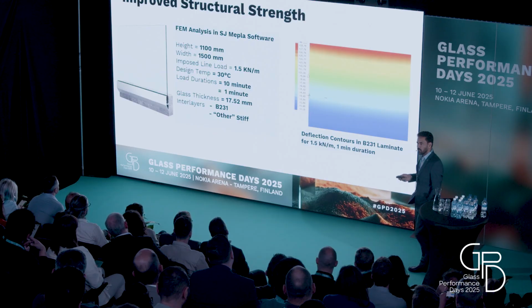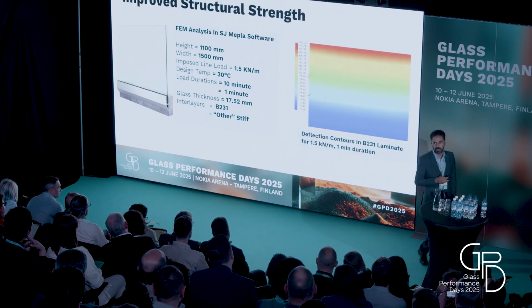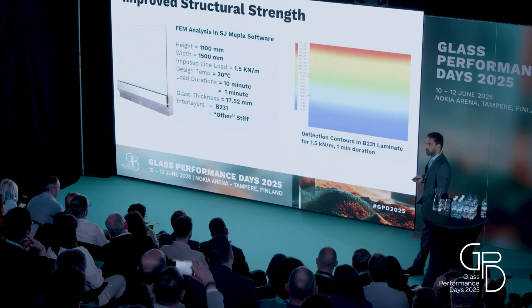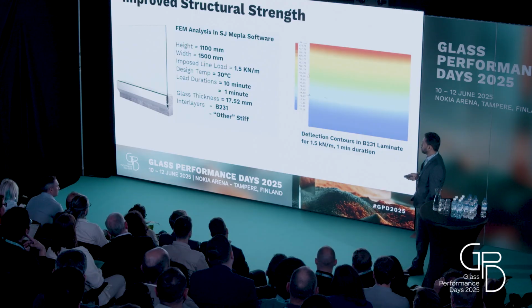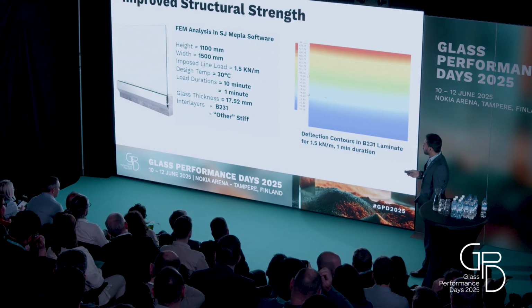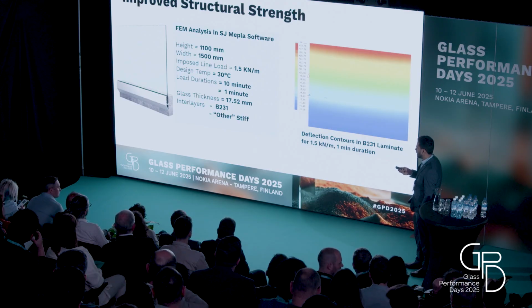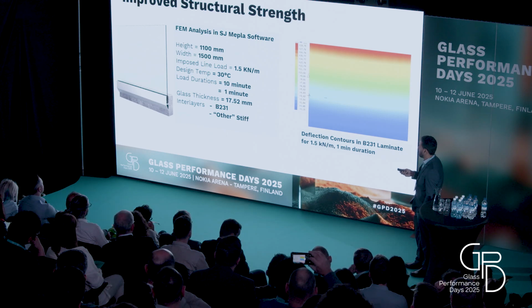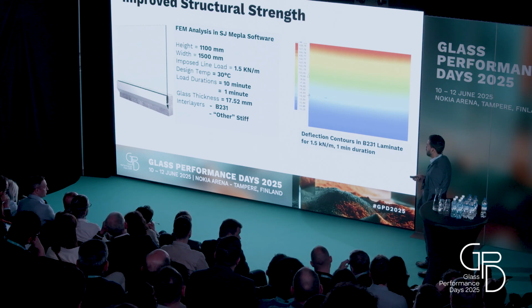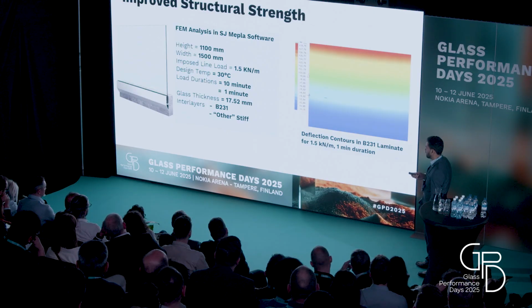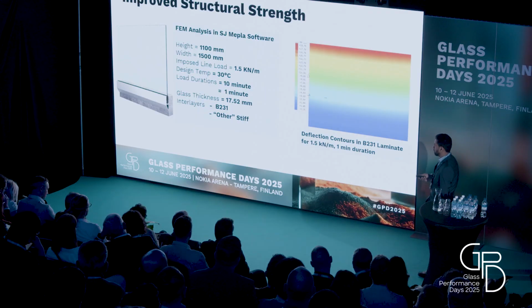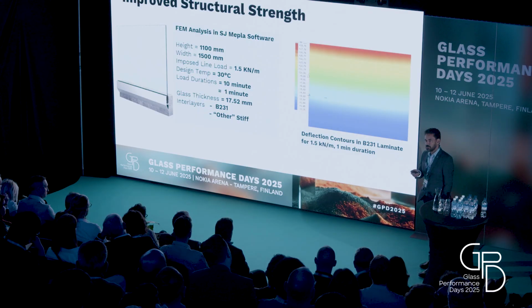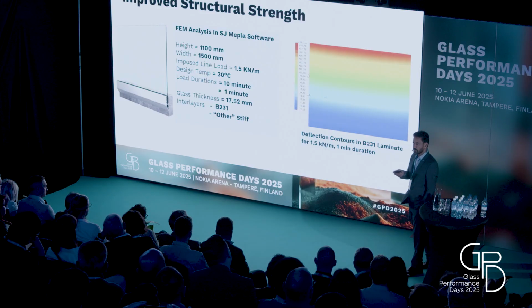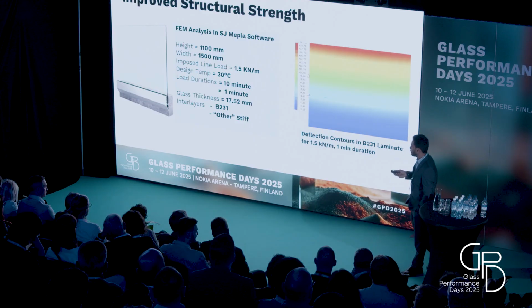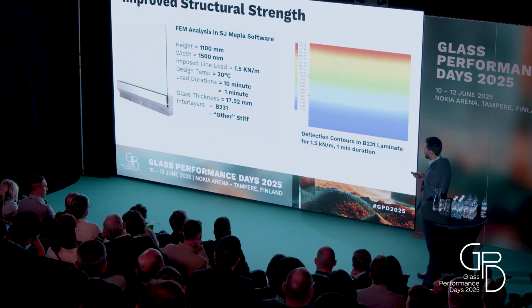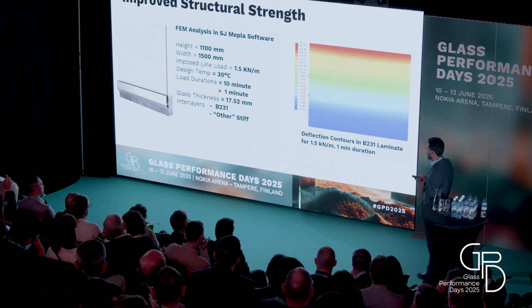Now we have seen that this improved stiff PVB has a higher Young's modulus, and the question is what this can do for the engineers. The first step is to do a finite element simulation in Mepla software. I analyzed a cantilevered glass balustrade, supported at the bottom edge with a linear support, with a standard height of 1.1 meters, subjected to a line load of 1.5 kN per running meter, and a design temperature of 30 degrees centigrade. I analyzed two different load durations, 10 minutes and 1 minute, because the duration of the live load varies between country standards. The construction was 17.52, with the interlayers being B231 and the other stiff PVB.